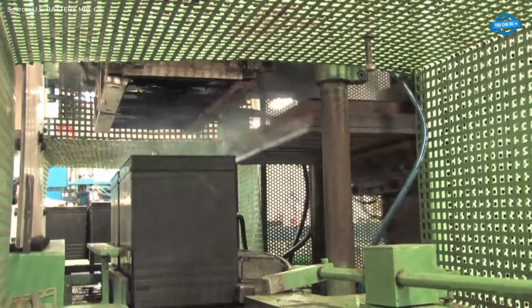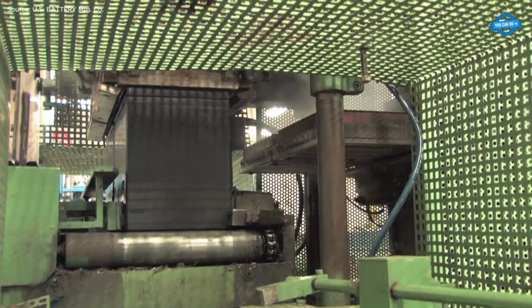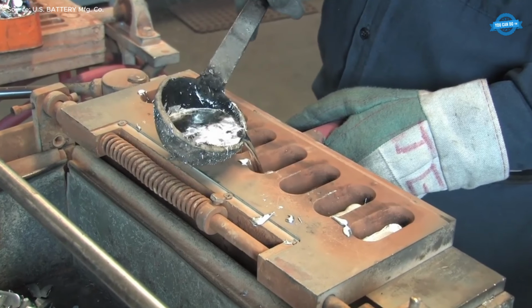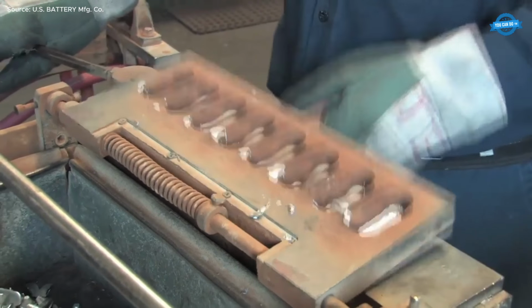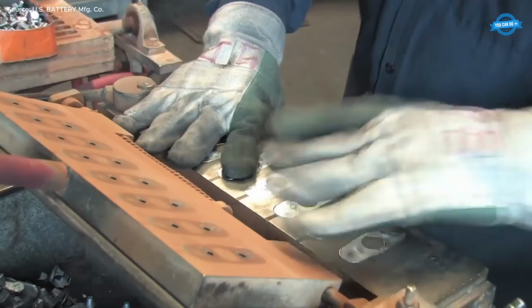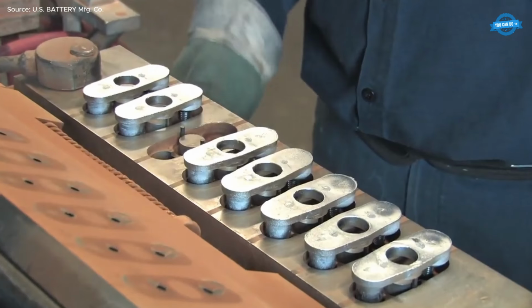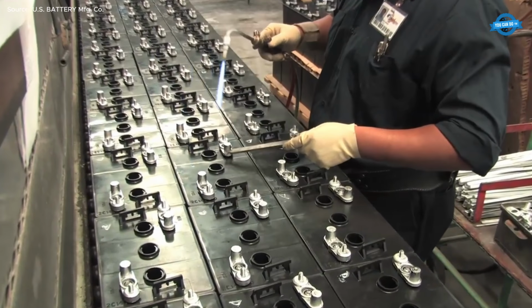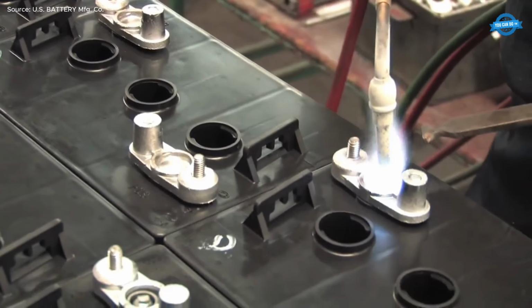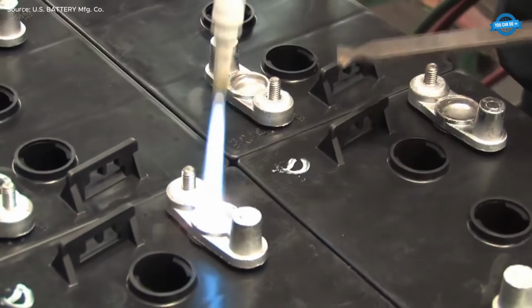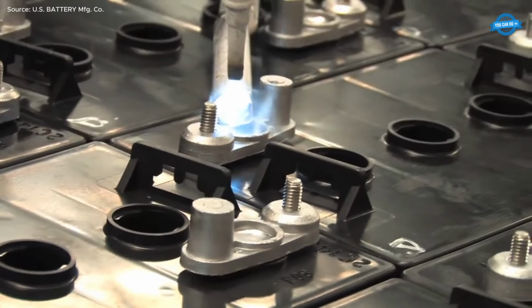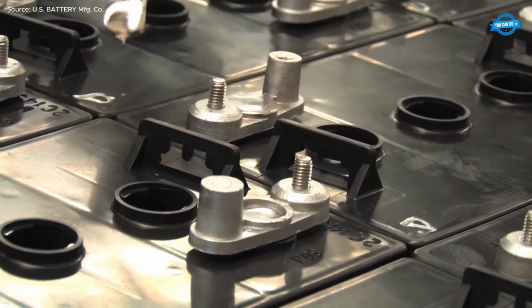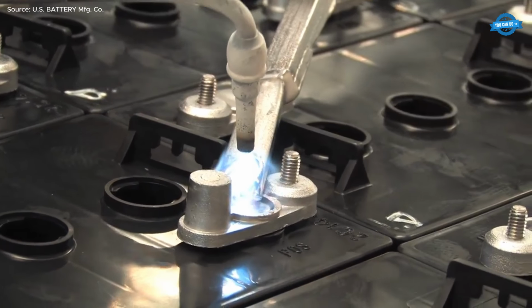In assembly, cured plates are hand-stacked with separators to form cell groups. Skilled technicians fabricate and fit lead strap connectors and intermediate terminals to ensure low-resistance current paths. Cell groups are inserted into polypropylene cases and welded using automated equipment. Every battery undergoes high-voltage short-circuit checks and weld integrity testing before heat-sealed covers are applied.